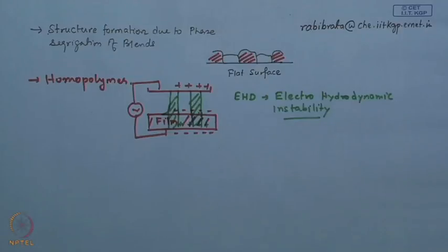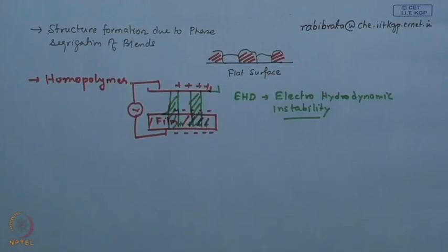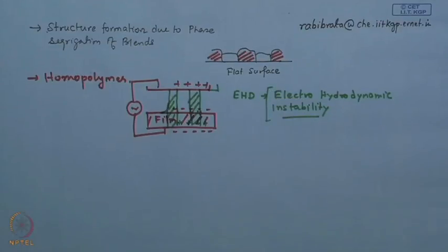And this again acts due to the externally applied field. The advantage is that you are applying an additional field from outside. So, you have the ability now to control the strength of the field, and therefore, you can destabilize films which are much thicker, in the context that films with this type of thicknesses will never show a spontaneous instability like dewetting.